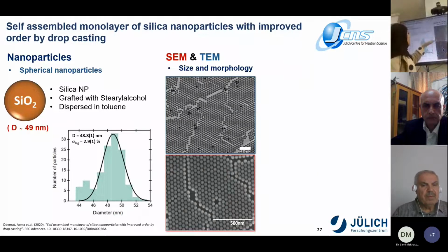From both images, we can see these particles have a regular spherical shape, and once deposited on the surface, they tend to organize into a two-dimensional hexagonal lattice. Manually, I calculated the mean diameter of this particle and the size distribution using the log normal size distribution, which ends with a particle around 49 nanometers and a size distribution less than 3%.